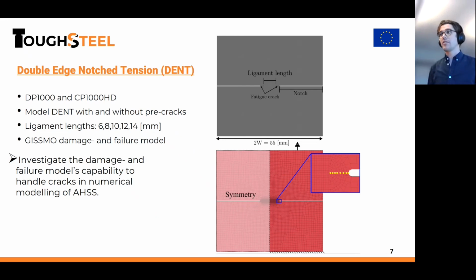In this study, two high-strength steel grades with similar strength but slightly different ductility were investigated. The effects from cracks were investigated through numerical modeling of double-edge notch tensile specimens, or DENT specimens. We used one set of DENT specimens with fatigue cracks grown from the notch ends, and one set of specimens without the fatigue cracks, which we simply call notched specimens. Then we performed numerical modeling of this test, validated and correlated against the corresponding experimental results. We did this for a large number of ligament lengths, ranging from 6 to 14 millimeters.